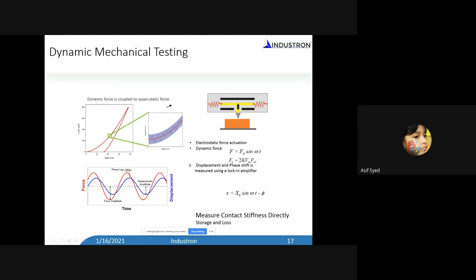What I mean here is, let's say when you apply a sinusoidal force, which is this red sinusoidal curve, and then you measure the displacement response, which is the blue curve, if there is no phase shift, for example, when you do it on typical metals, you won't see any phase shift.